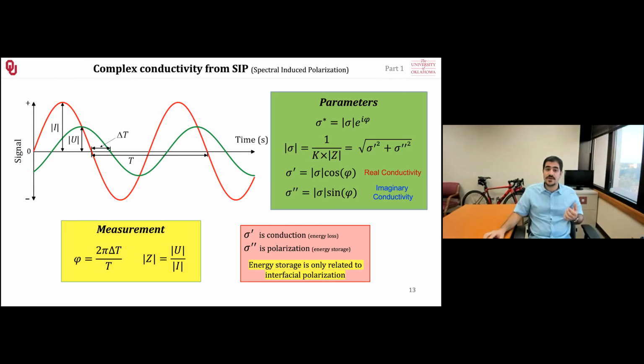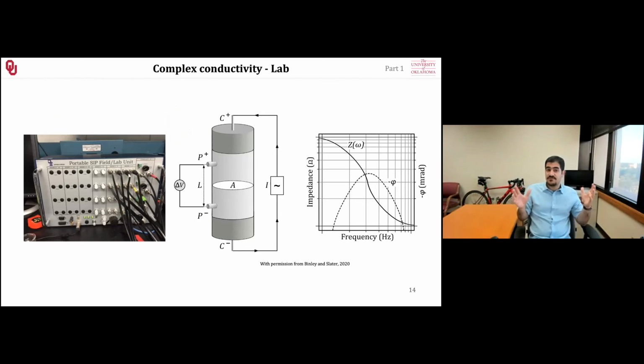And based on that, we can get the real conductivity, which is the conduction, for instance, through the pore filling fluid, and the polarization, which is the energy storage because the ions were redistributed and got polarized. We get these two in both lab settings and field setting.